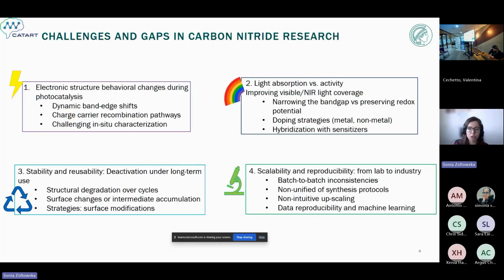Another quite important issue to solve is related to stability and reusability. We know that carbon nitride can structurally degrade over the cycles. We observe some surface changes and some intermediate accumulations, so we're trying to develop some surface modification strategies. And finally, scalability and reproducibility. We observe batch-to-batch inconsistencies, especially for the bulk materials. This can be solved by using them in the film form. Some synthesis protocols are not unified. The scale-up is not very intuitive. And of course, here we are trying now to introduce machine learning to avoid all those issues.